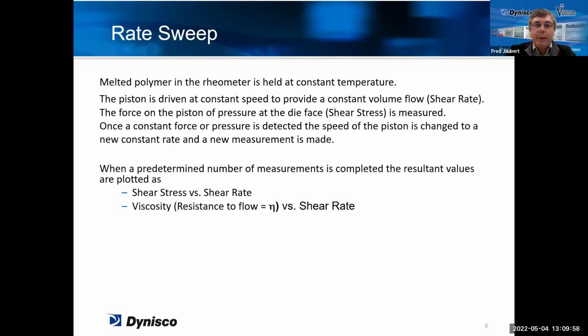First of all, what we call the rate sweep or shear sweep test is the test where we are going to vary the shear rate. So the polymer is melted into the rheometer, and this is done at constant temperature. In a capillary rheometer, you cannot really change the temperature during a test. You can make tests at different temperatures, but for one test, you can only run at one temperature. And what we are going to do is we are going to give constant speed on the piston, and this will generate a constant flow through the capillary. And we are going to measure this force or this pressure that we need to generate to be able to be at a constant flow.